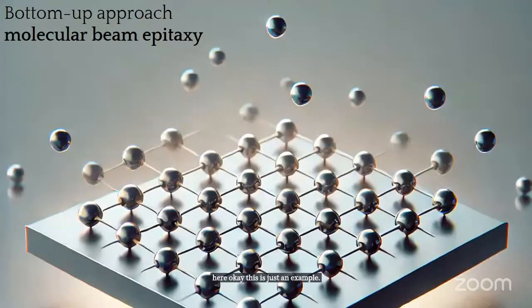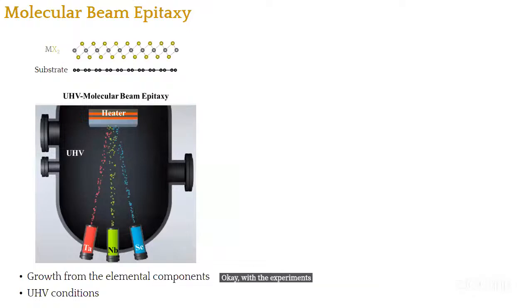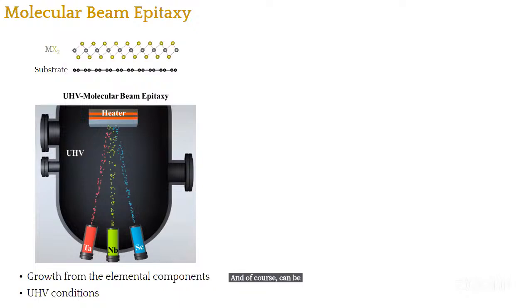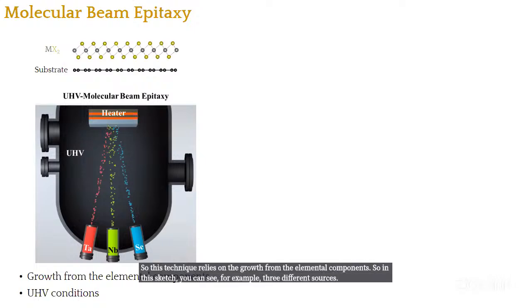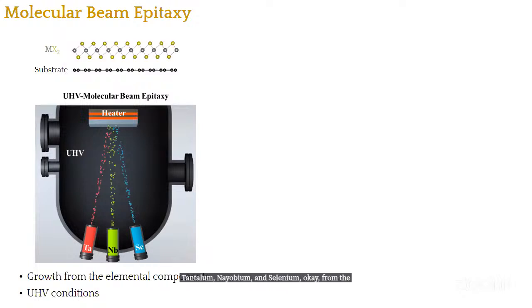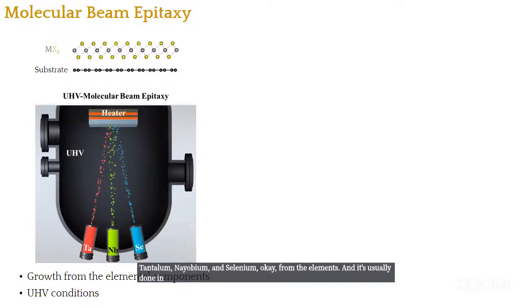Now let me get started with the molecular beam epitaxy materials that we grow. Molecular beam epitaxy is a very versatile technique for the growth of thin films in general. It's been known for many years, and of course can be applied to the growth of 2D materials. This technique relies on growth from the elemental components. In this sketch, you can see, for example, three different sources: tantalum, niobium, and selenium. It's usually done in ultra-high vacuum conditions to maximize the cleanness of the resulting thin film.